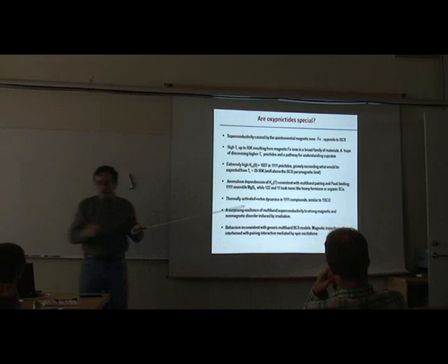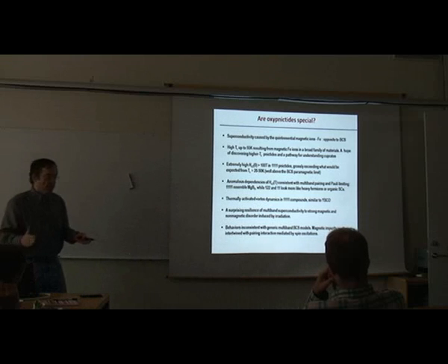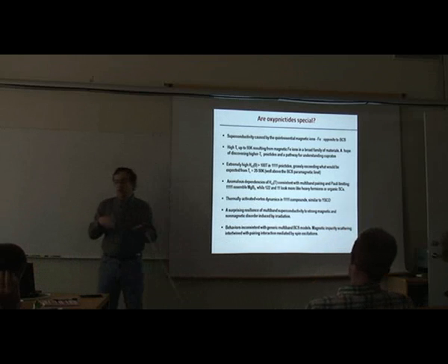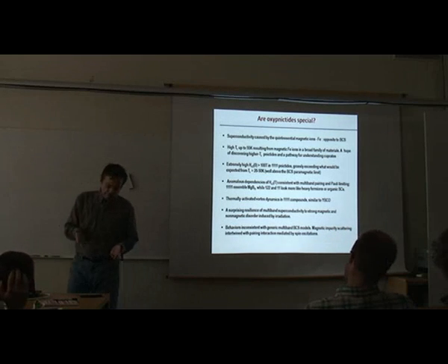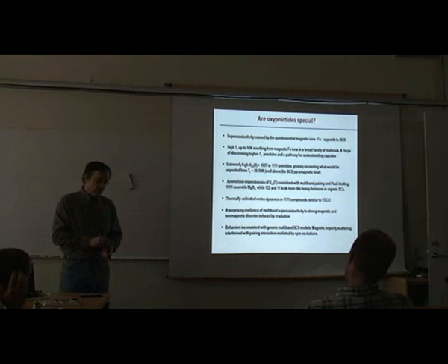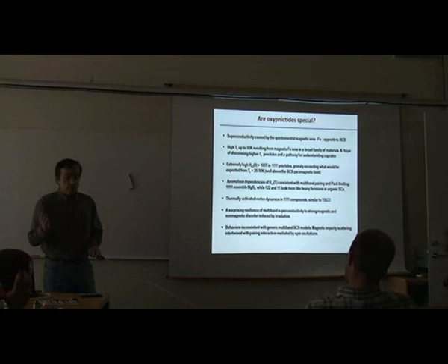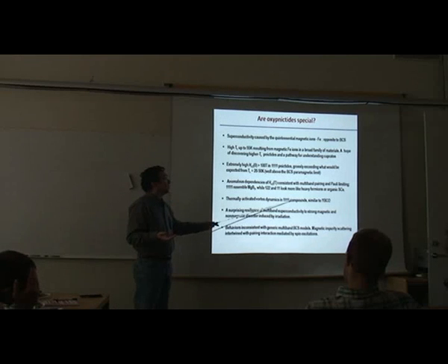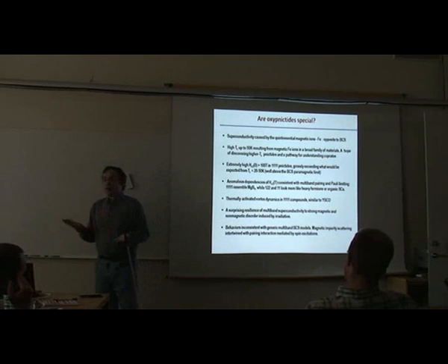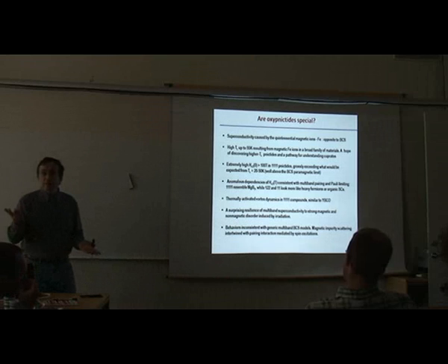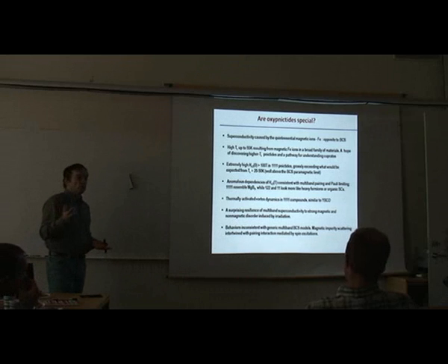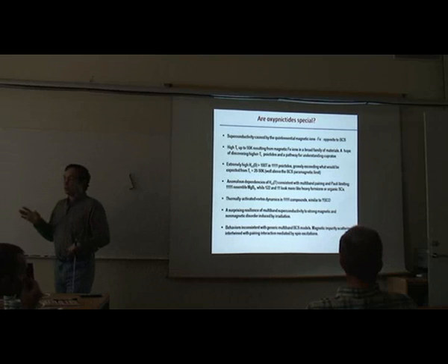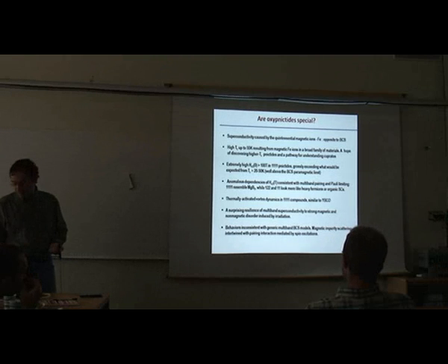Then basically within this family of pnictides you can go from very classical behavior in terms of vortex dynamics. Let's say low Tc members of the family behave like conventional superconductors like niobium as far as thermal dynamics is concerned. The high Tc materials like this guy behave more like YBCO, like the cuprates, with a strong thermal activation of vortices, giant flux creep, vortex melting, and all these features you can actually see in pnictides.